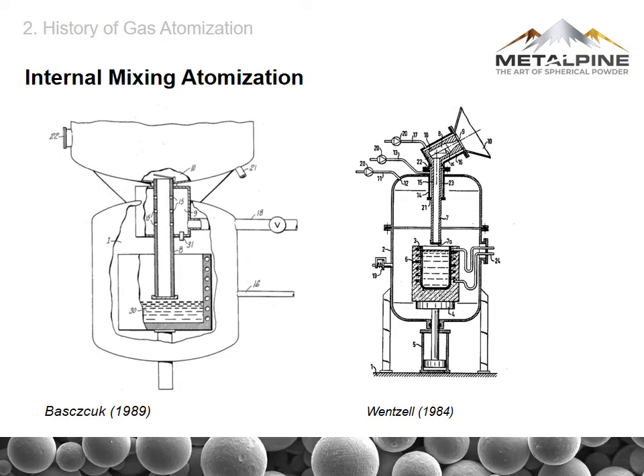Internal mixing atomizers are commonly used, for example, for heavy fuel burners, and not so much for melt atomization, but there are also some patents and developments in this direction. You can see here, for example, a method filed by Basczcuk 1989. The rising pipe has got some holes on top where the atomization gas is introduced and mixed with the molten metal, which rises due to the pressure that's in this tundish. The atomization is vertically upwards. A comparable system was also filed by Wentzell, where on the top of this pressurized tundish there is some atomization and mixing with the gas introduced into this nozzle head.